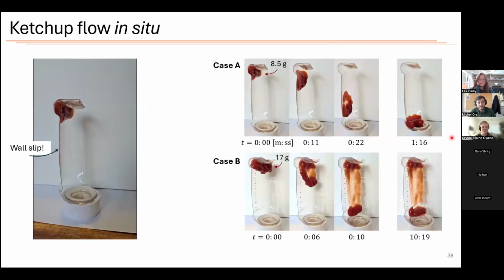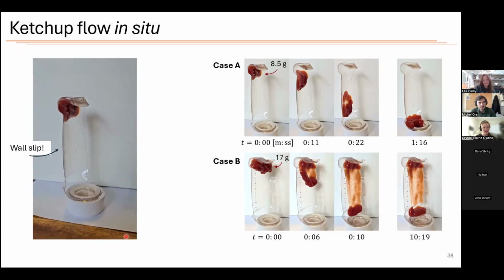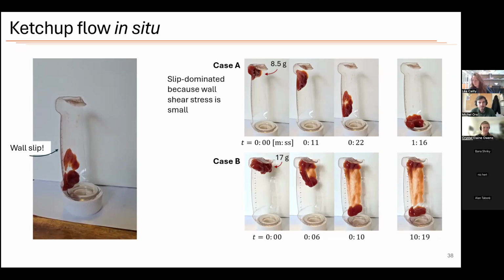So now we can bring this together to more or less conclude our findings of what's happening here. So we can watch this video again just to see what's happening. So this is, again, clearly dominated by wall slip. And that's basically all of what's going on here, is there's little enough ketchup that there's no internal shear, except maybe a little bit at the end here. But then it's just sliding and then it's coming free without leaving basically any residue. So this is great because it leaves the bottle clean, but it's bad because it takes a lot of time.